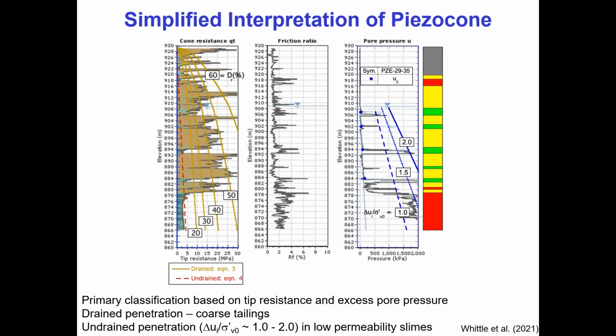But just to be very simple about this, we have a primary classification here. We assert that when there are no excess pore pressures, the piezocone is measuring drained penetration conditions and is likely associated with coarse tailings. When there is excess pore pressure, we expect it's going to be slimes. The highest excess pore pressures will be associated with slimes. That accords with the color scheme you can see on the background on the left.